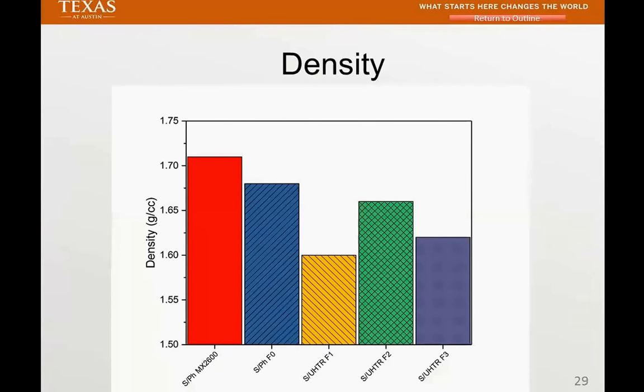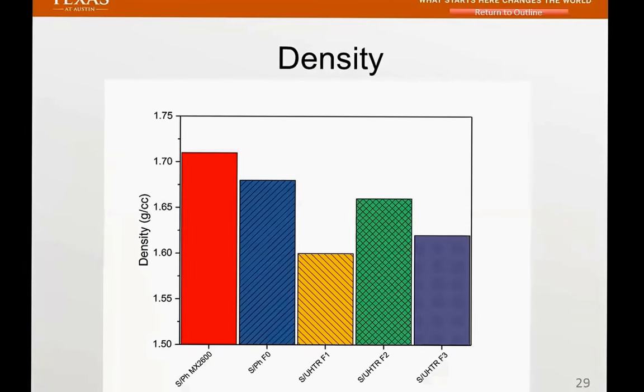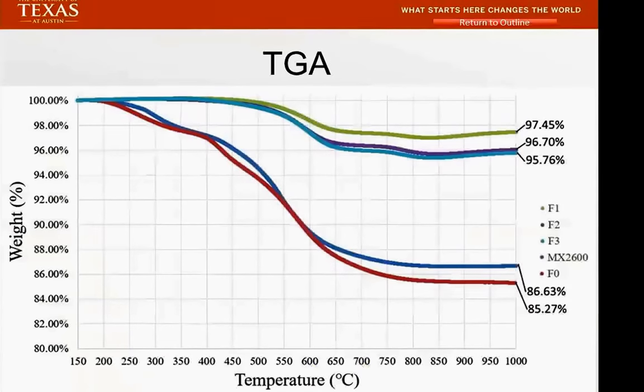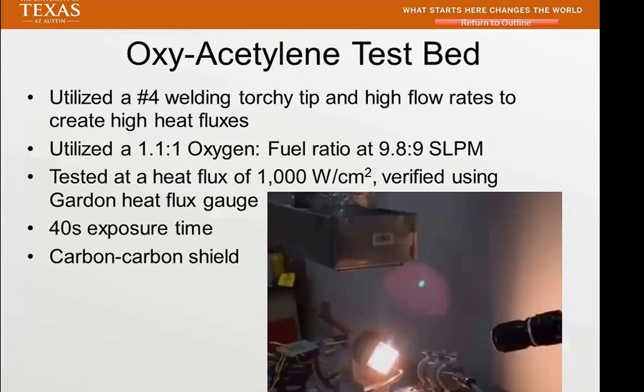And the density. Well, it's showing that all of these have lower density than the control MX2600. So if we have a low density, you have a better performance, you have weight saving. Okay, so we do TGA. First, I did it for the resin. Now we're actually doing it for the composite. Take a look at the composite. It is very, very high, 97%. That's extremely high.